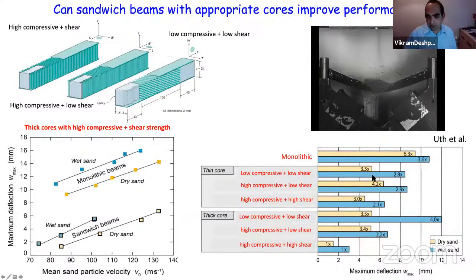And here we are showing, for example, lots of different types of configurations of sandwiches. And so let's just focus on these thick core sandwiches, right? Everything has the same mass first, I should say, right? So it's a sort of fair comparison, same mass, same size, etc. If you use the blue bar chart as the baseline at high strength, if you then decrease the shear strength, you've increased the deflection by a factor of 2. If you then decrease the compressive strength as well, you've increased the deflection by a factor of 4.